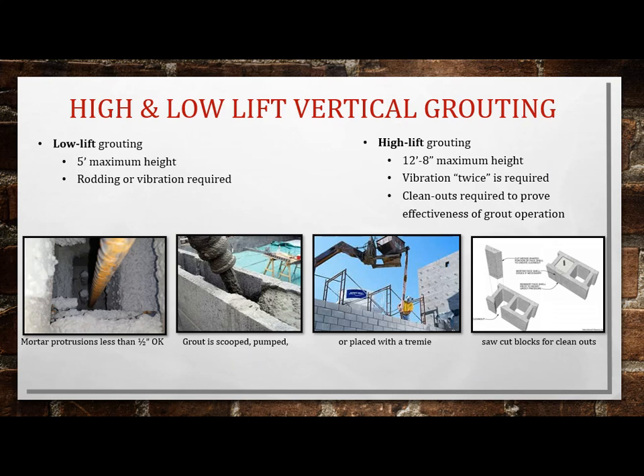This is for vertical grouting. And the specifications will say it's either got to be a fully grouted wall, grouted on 16 inches, 32 inches, whatever. So it'll be specified. And so there's low lift grouting, which is kind of preferred, and it's limit 5 feet. Normally it's done at a bond beam and below, and then you build up, and then you would actually grout. The grouting for a level is a continuous operation, and you still have to puddle or vibrate the grout in the cells.